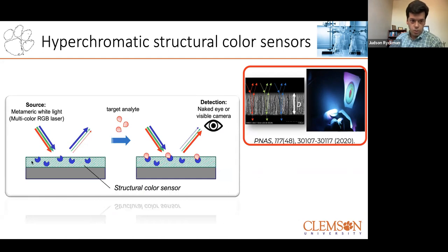So we use it as sort of our sensing substrate, if you will. And we came up with this technique called hyperchromatic structural color, where instead of shining ambient light or white light on a sample, we're going to illuminate it with laser light, and specifically at least two different wavelengths of light. In this case, I'll show the RGB case, so red, green, and blue laser wavelengths. We have a porous silicon film, which serves both as a host to capture small molecules, but also as an optical film that has tunable properties. And it has a reflectance spectrum that will shift or perturb in response to these molecules.